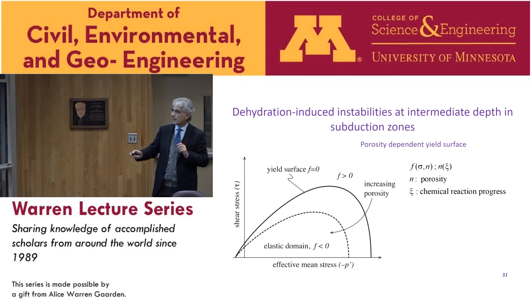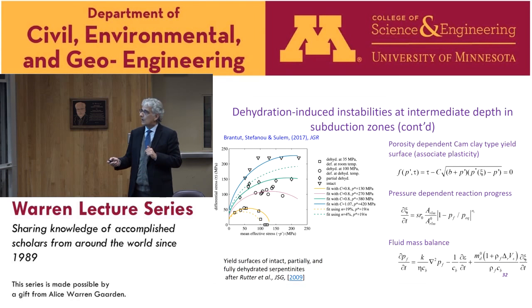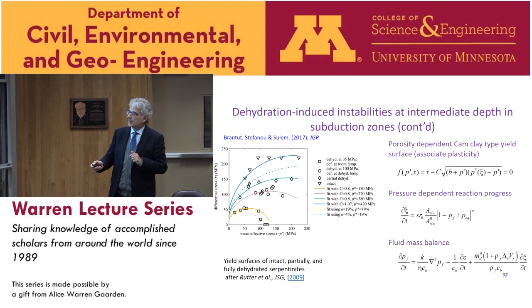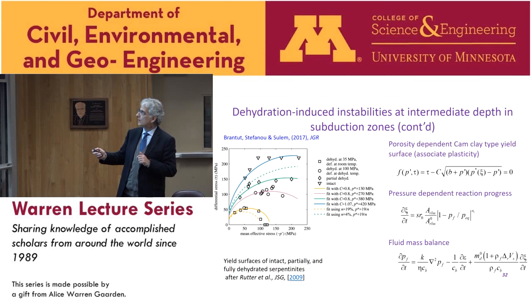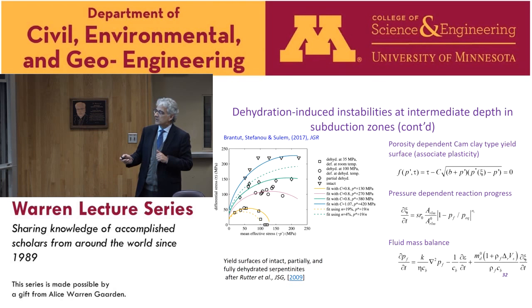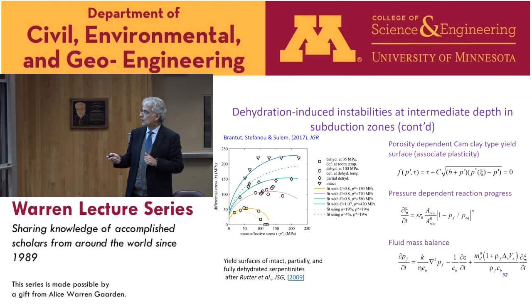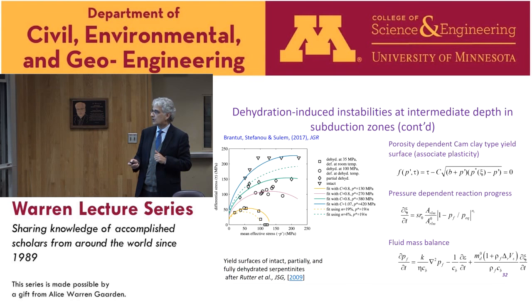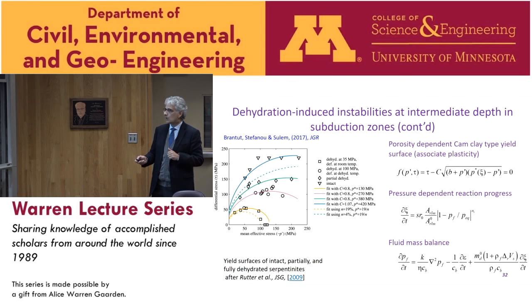For the modeling of that, we take a porosity dependency in the yield surface. n is the porosity, and n depends upon the evolution of the chemical reaction. We took the experimental results, and we have calibrated a Cam-clay type of yield surface, assuming associated plasticity. To describe the kinetics of the reaction, we consider a pressure-dependent reaction progress. So this is how the pore pressure is controlling the actual rate of the reaction. And this is the fluid mass balance. It's like before. We have the diffusion, we have the mechanical term, and this is the effect of the additional fluid phase which is introduced in the system.